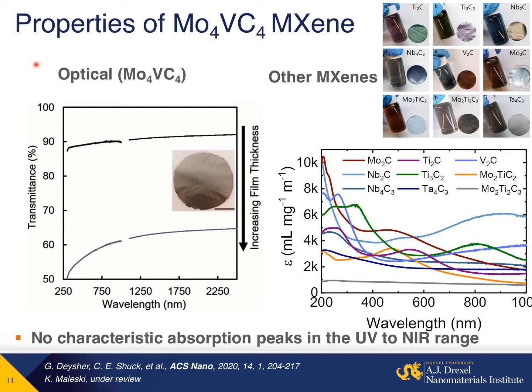This is very unique, and it allows us to make devices for applications that no other MXene or really many materials can do. This is very valuable for optoelectronics because you can make spray-on transparent antennas. If you spray this material onto a perovskite on top and under, you can make electron transport layers that do not significantly change the light reaching the perovskite. If you were to remove ITO, you can make flexible electronics if you would spray it onto plastics or other flexible substrates. So by not absorbing really any light from UV to near IR, this opens up a new pathway to produce a wide variety of optoelectronic devices that no other MXene can do.